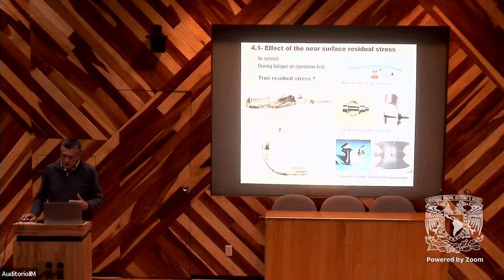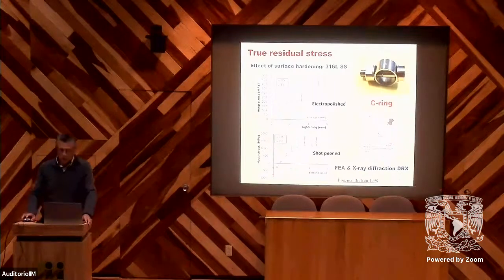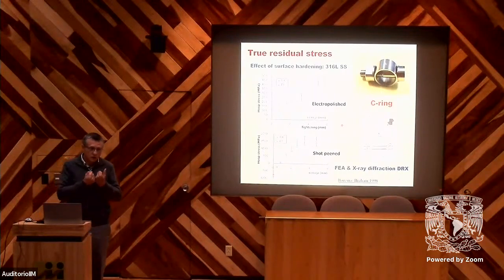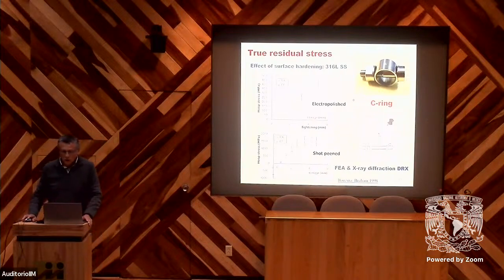So all seems very simple, but the problem is how to determine the real residual stress state, because we need to take into account the effect of deformation and also the initial states, that means the hardening and also initial residual stresses. If you have, for example, a grinding at the beginning, what happens when we apply stresses? This is the first question. This is an example of results using calculation by finite element analysis, and also by measurement using X-ray diffraction at the apex, at the external skin of the tube.